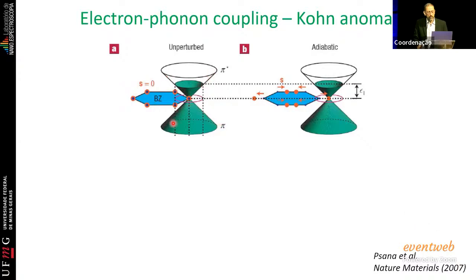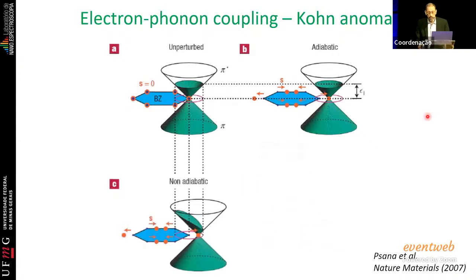Here we have the Dirac cone structure of the electronic structure of graphene. In this case, graphene is a little bit doped, so you have electrons up to here, okay? Where it is green is where you have electrons, filled up to here, and above are empty states. So usually when the atoms move, as in the carbon-carbon stretching, we always use the so-called adiabatic approximation. We just consider that electrons are too fast and phonons, the atoms, are too heavy and too slow, okay? So we treat electrons and phonons separately, and we extract all the information without considering electron-phonon interaction. However, these fellows introduced this very nice cartoon.